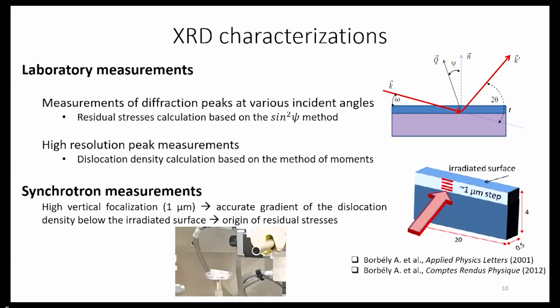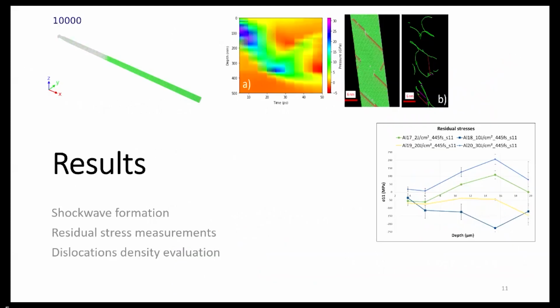We are also doing synchrotron measurements, which allow us to focus the X-ray beam a lot more and get an accurate gradient with a 1 micron step. So let me present some results. First on the shockwave formation with the simulations, and then on the residual stresses and dislocation density evaluation.